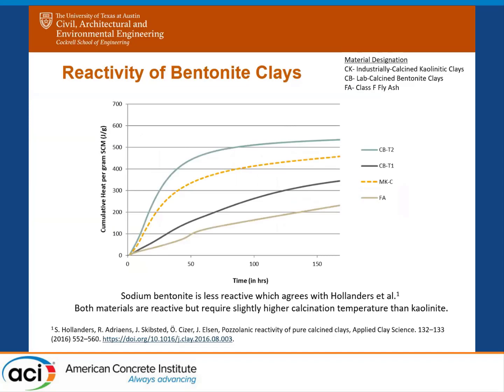So the bentonite clays, so here we have the two bentonite clays that the supplier is from Texas, and also a fly ash as a control, and the MKC, which is one of the moderate purity clays. So this is really just showing that these montmorillonite-based clays are also reactive and could be viable if that's what's locally available. So the sodium bentonite, which is CBT1, it was less reactive, which agrees with previous literature with Hollanders and other authors. But both of these materials are reactive compared to the moderate kaolinite clays.